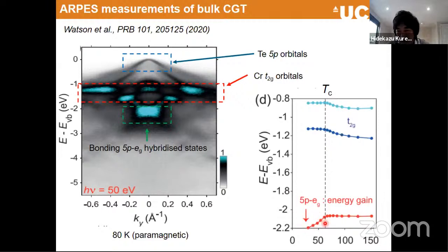And then their proposal was that this is gained by the local ferromagnetism, and that drives the ferromagnetism. So initially I thought that T2G and p-pi hopping can be the one to drive the magnetism. But when you look at the T2G state, we cannot see a significant change in the band position. So I still believe that this is a driving force, probably different from the typical Kanamori-Goodenough 90-degree rule.